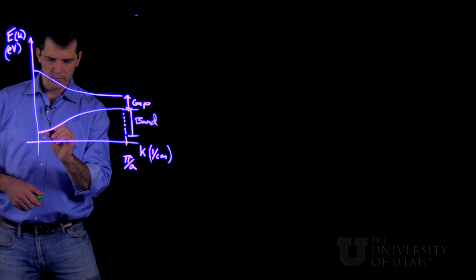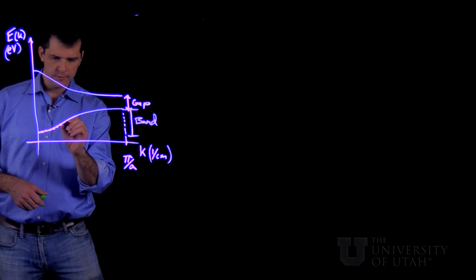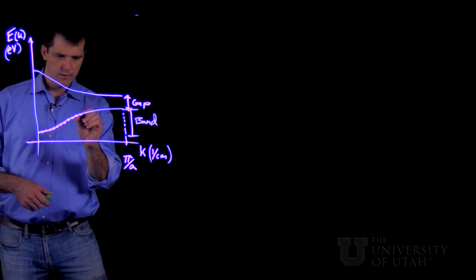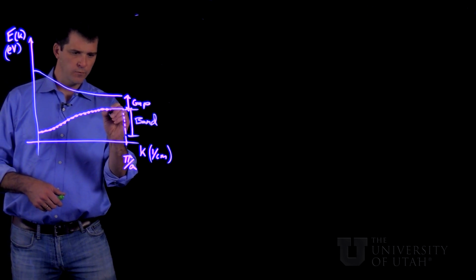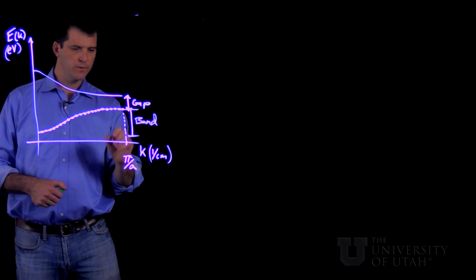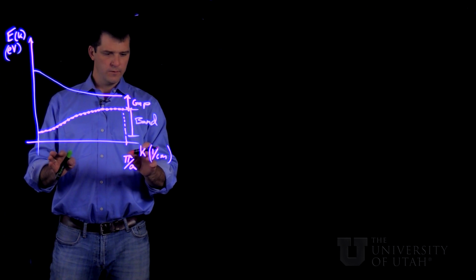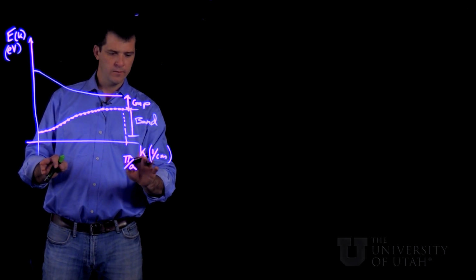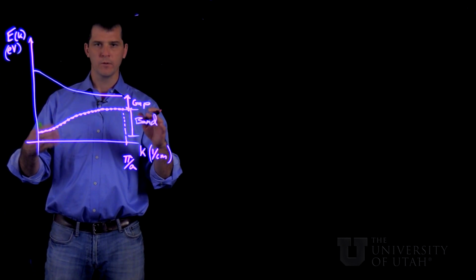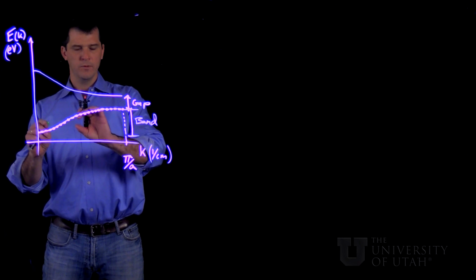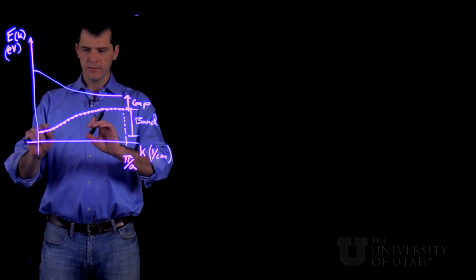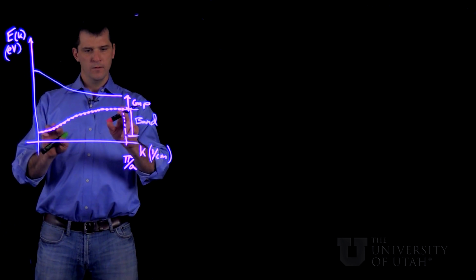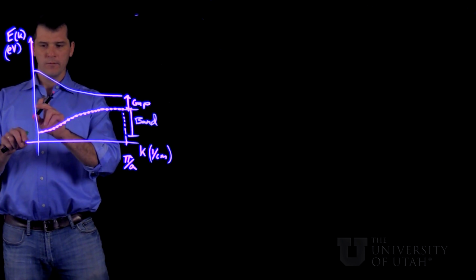And you have to remember that this is actually a discrete band of solutions. Each atom in the crystal adds one solution to this band. So we have to take this k not as a continuous variable, but quasi-continuous, because it's discrete but a very large number. And so there's actually finite k values, each one having its own energy.